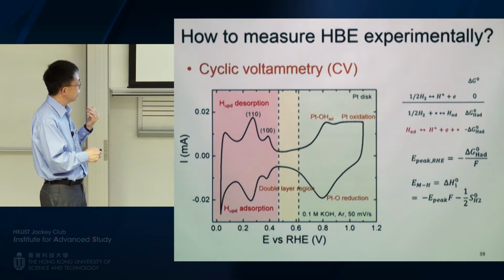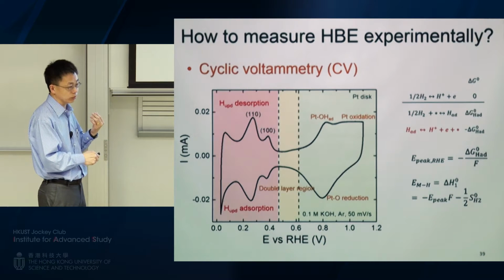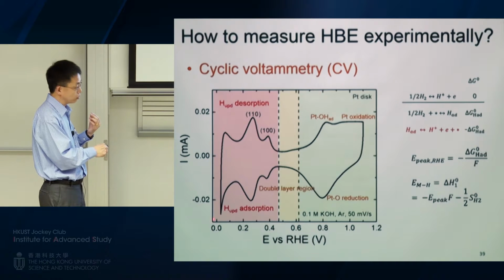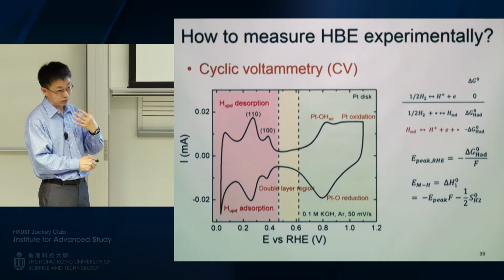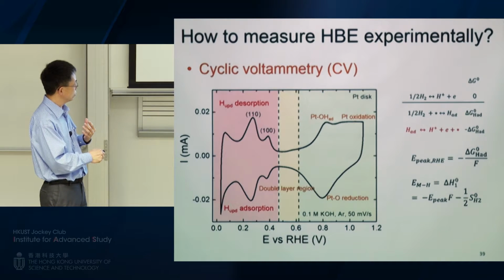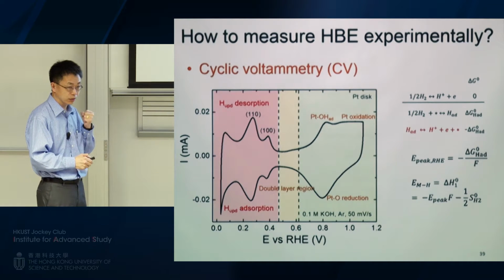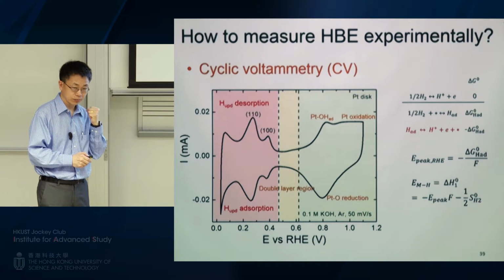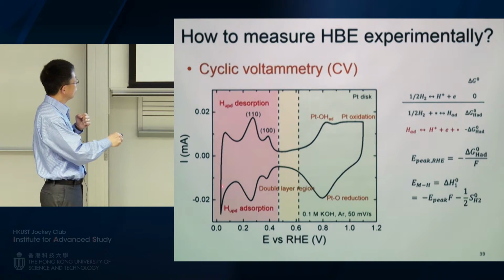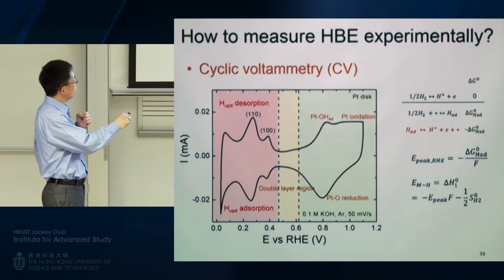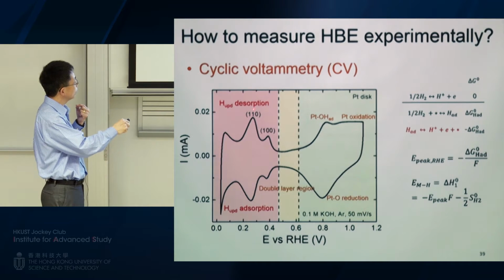And the reason we call this underpotential deposition is because it occurs at a potential where hydrogen is not supposed to be reduced. So this is higher than the zero potential. Usually at zero potential, that's by definition, you get your hydrogen out, but it happens earlier. Just because hydrogen really, really enjoys being on the surface of platinum. And then when you reverse the potential, you start oxidizing the atom on the surface, and then you do the discharge, turn it into a proton, give up the electron to the electrode. So you call this the desorption peak.